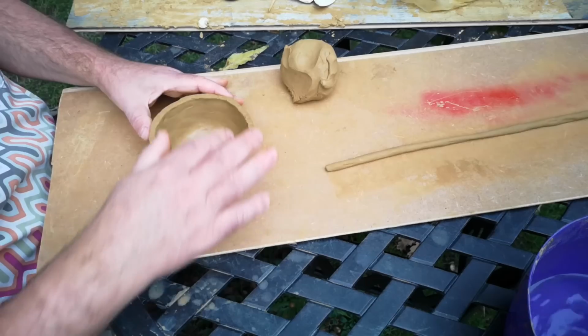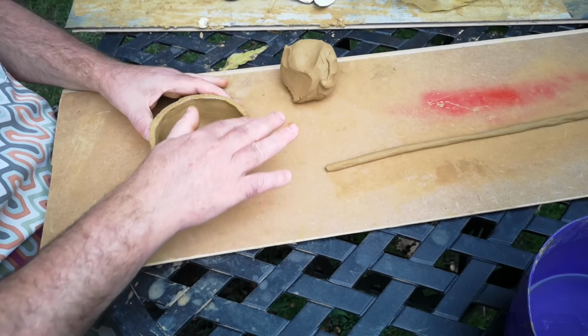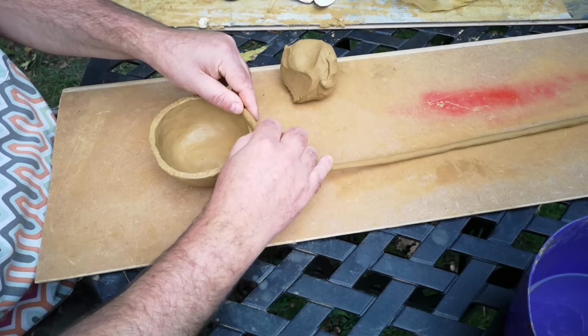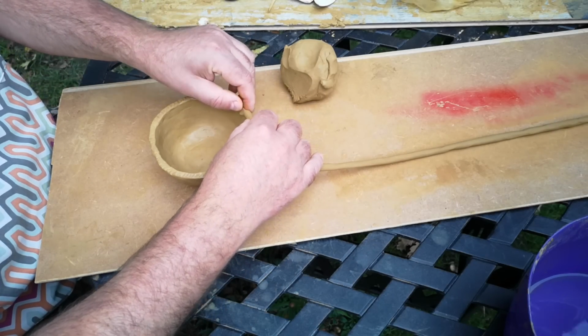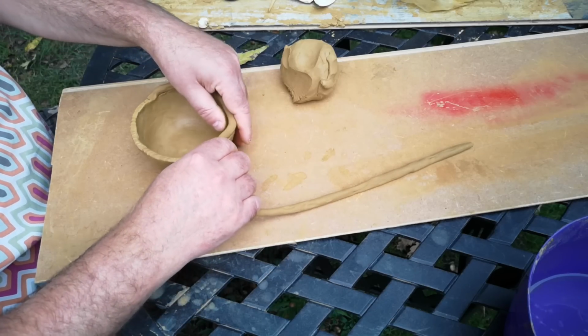In fact, I think some of it might be burning out. I suppose if there are minerals such as iron sulfide in there, which is possible, then the sulfur might be just burning off. The iron would still be left behind, probably in oxide form, but if there's material actually burning out of the clay, the result might be a more porous and open texture like I'm seeing.